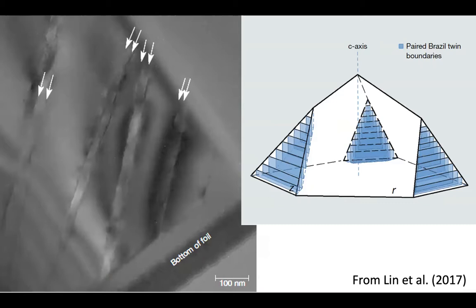Or if there are impurities that are, in a sense, creating strain from within, because the impurity elements have a different size than silicon does, then Brazil twins can also be generated. And that strain field gets released, in a sense, by the generation of these Brazil twin boundaries, which are kind of storing the strain energy. And so they are very regularly spaced. And those impurities that might be responsible for the creation of the Brazil twins, they tend to diffuse. And once they get to the Brazil twin boundary, it's a very hospitable environment, and they stay there